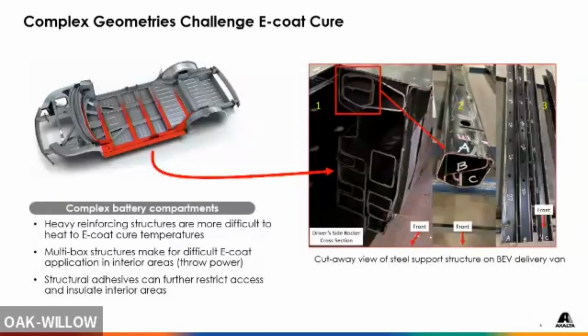The problem is a 160 degrees C coating is pretty standard. It's been around for 30 years. To go from 160 degrees C to 140 degrees C is an invention. Going from 160 degrees C to 150 degrees C is still within our formulation toolbox. We can play around with the catalyst, the crosslinker level, and some of the additives, and we can achieve 150 degrees C cure, no problem. But we want to drive from 150 C to 140 C. That requires innovation and, quite frankly, a new system. So this is our challenge as far as e-coaters, what we're trying to accomplish. We want to get to 140 C into some of those very heavy reinforced areas.